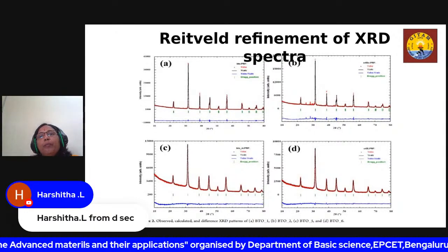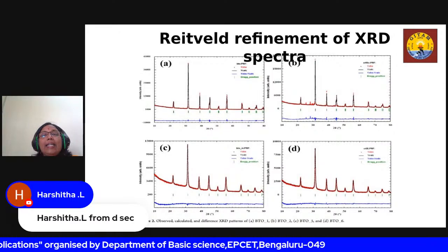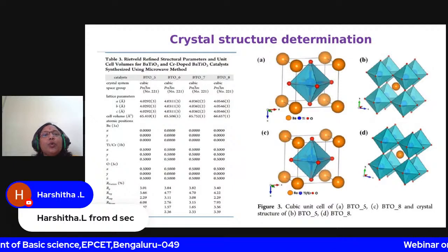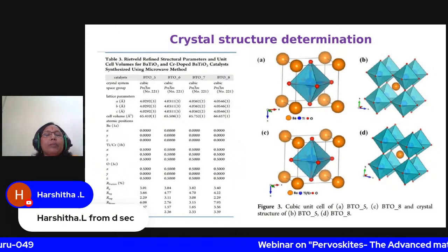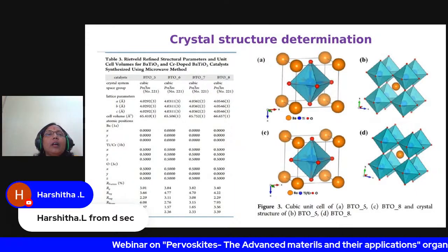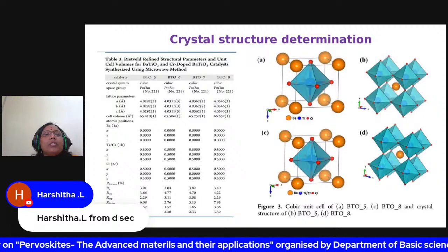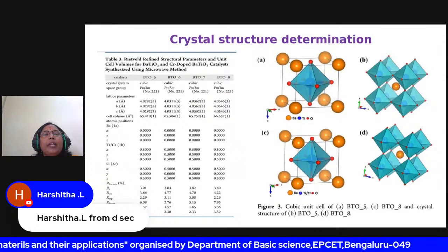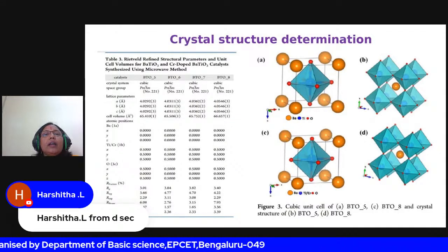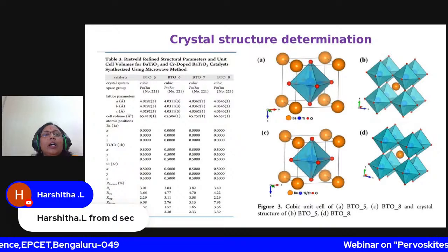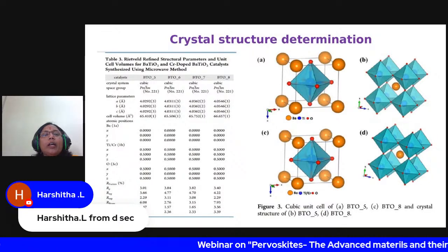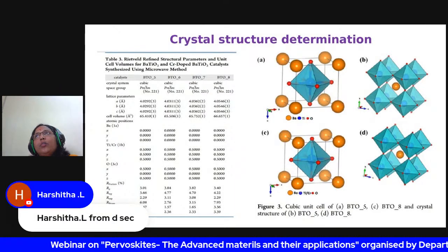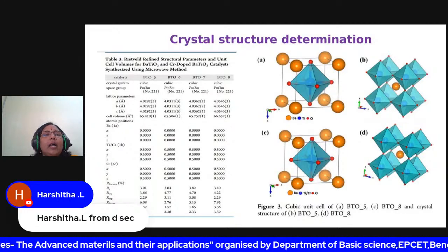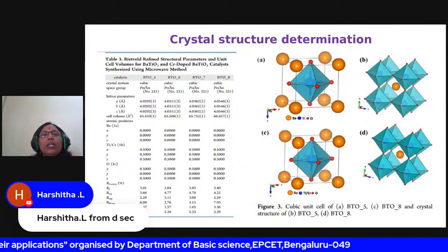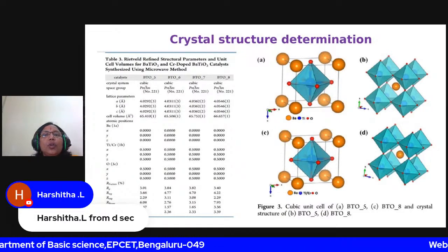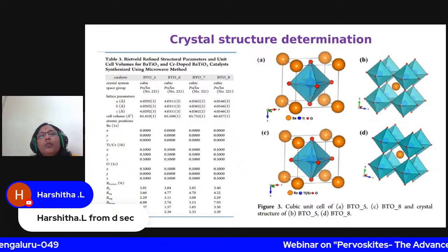And along with this, the crystal structure determination and also the lattice parameters we can get. For example, in the next slide I have shown whatever parameters we have got from the Rietveld refinement of the microwave synthesized samples. The refinement results further confirm that the cubic phase of barium titanate is present in the microwave synthesized samples, and the lattice parameters increased with increase in the chromium content in the sample, which is obvious because the ionic radius of chromium is slightly higher than titanium. That's the reason the cell volume also increases with increasing chromium content, and the lattice parameters also increase. So with this information, we can model a structure.